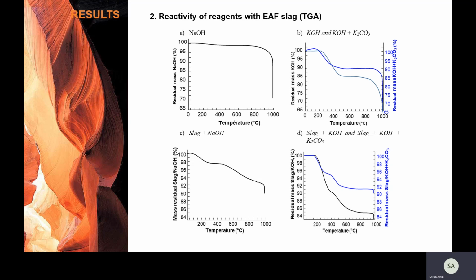Mass loss clearly indicates a reactivity of the alkaline reagents with the slag, which induces the formation of compounds which are more thermally stable than the alkaline reagent. It should be noted that the slag, which consists of compounds obtained at high temperature, does not undergo such a treatment and does not generate a significant loss of mass. These results led to the choice of treatment temperatures used in this study, which are between 400 and 800 degrees C.